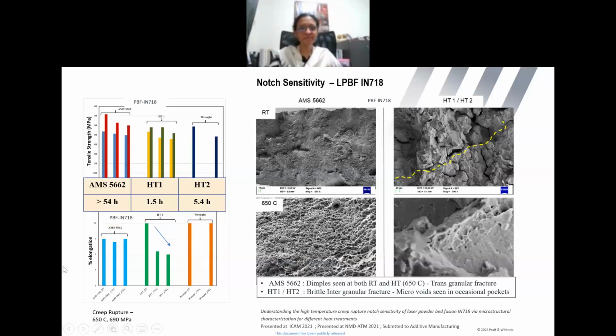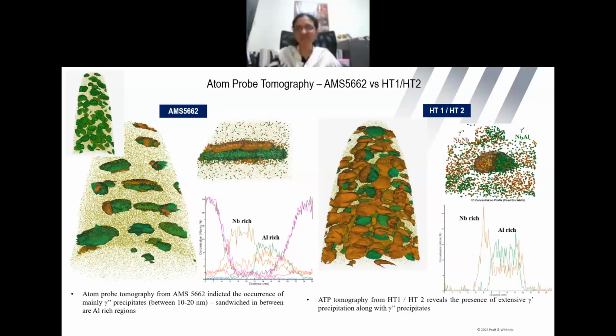And then, if you look at the high temperature, what the additive shows in terms of the creep rupture at 690 megapascal and 650 degrees centigrade, it lasts only for 1.5 hours. Whereas the equivalent wrought product is lasting for more than 50 hours, an order of magnitude higher notch sensitivity. So we solved this with very, very high-end advanced characterization techniques. This is an atom probe tomography. Not sure if the video is going to work.